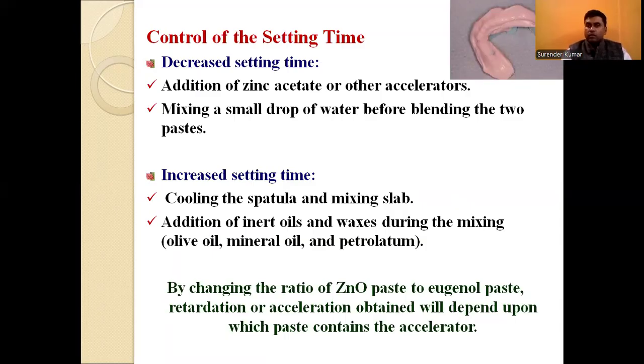Control of the setting time: how can we control the setting time? If you want to decrease the setting time, you can add zinc acetate or other accelerators. It will quicken the setting rate. Or we can also add a small drop of water during manipulation.